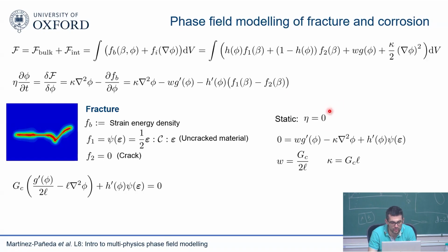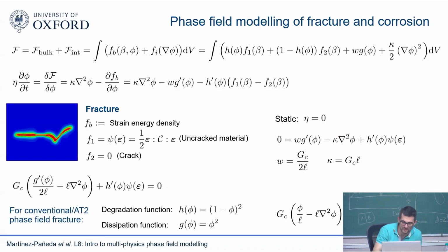So we normally take this guy to be equal to 0, and then when you make this equal to 0, you end up with this expression. You make also F2 equal to 0, you kill it here. And then you can see that if I look at the phase field fracture equation that I've been discussing the entire week, I can define this W as GC divided by 2L, this kappa as GC multiplied by L, and I get an expression that is identical to the one that we have. So basically the idea is that you can come up with a generalized formulation that you can particularize to microstructural solidification, whatever you're interested in, but also fracture. So even though they were originated in a different way, they can be condensed in one formulation.